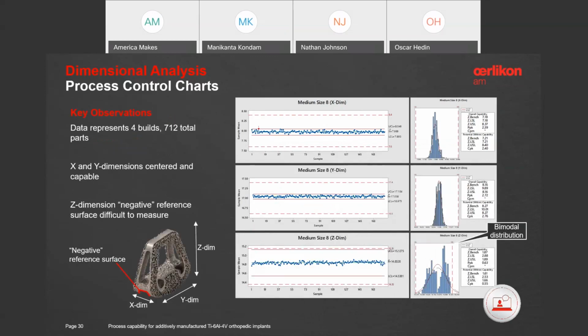Another challenge we frequently face are systematic measurement errors on account of part orientation. Overhangs and negative surfaces are inherently difficult to measure due to the increased surface roughness in these areas. And to make matters worse, the print for this plan calls out dimensions which are directly related to how well the operator has leveled the build plate. If you think the distribution for the Z dimensions in the bottom right chart looks bimodal, you're absolutely right. The two groupings represent different builds where the initial build plate setup has adversely affected part size, rendering one batch of parts undersized and the other oversized. And this highlights the importance of choosing robust quality features for inspection.